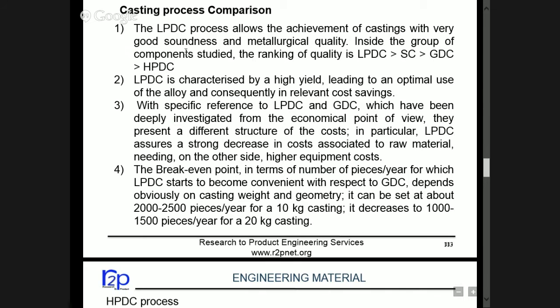Now this slide is very interesting. As you have seen, there are 4 casting processes in aluminium, right? From the casting quality point of view, LPDC results in the best kind of tensile property. Then the sand casting, then the gravity die casting, and then HPDC. Otherwise, it has been in our mind that HPDC may be the best process. But the castings made from HPDC, we are not able to heat treat. Heat treatable castings are by LPDC and GDC, right.